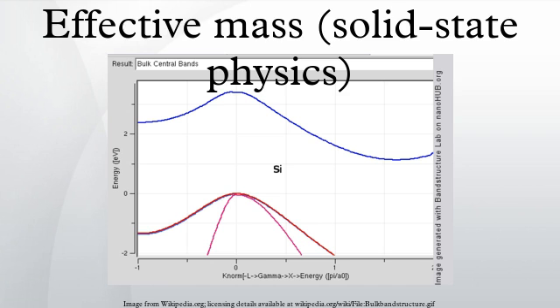Similarly, the number of holes in the valence band, and the density of states effective mass of holes are defined by... where EV is the maximum energy of the valence band. Practically, this effective mass tends to vary greatly between absolute zero and room temperature in many materials, as there are multiple valence bands with distinct and significantly non-parabolic character, all peaking near the same energy.